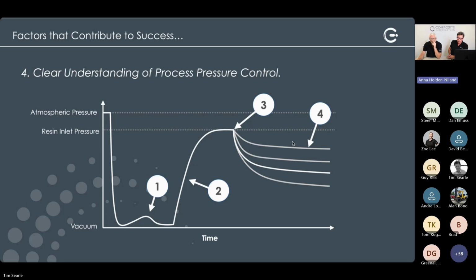And this is an important bit, because this is where, with particularly low viscosity systems, the pressure can start to reduce if it's allowed to bleed on. Not so likely with net fill infusions, but if we allow this pressure to fall a bit, we can gain a 2–3% fibre fraction. But the danger is if we let it fall too much, then the laminate does become much more susceptible to porosity.